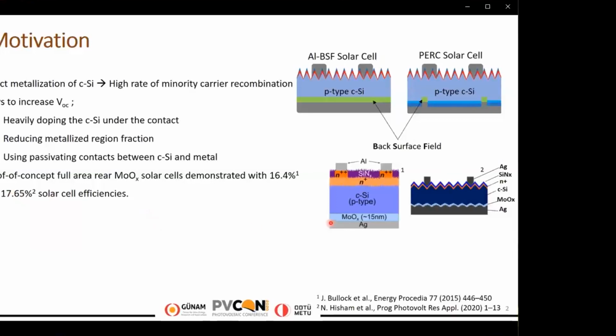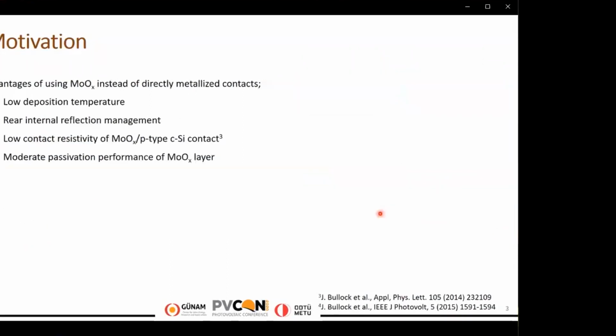So this study focuses on the latter two ways for VOC increase by applying a partial molybdenum oxide hole contact at the rear of the PERC structure. This substoichiometric molybdenum oxide's ability to form hole contacts is related to its large work function that promotes hole accumulation at these local regions created.